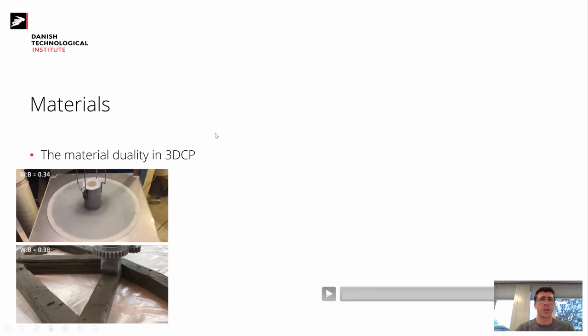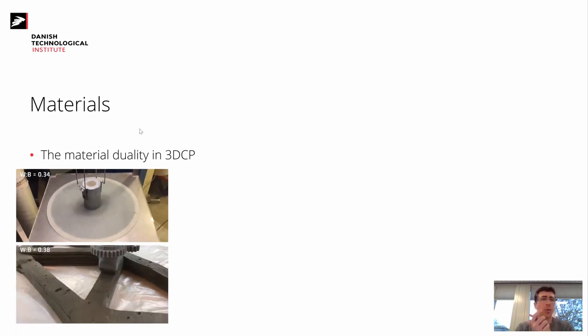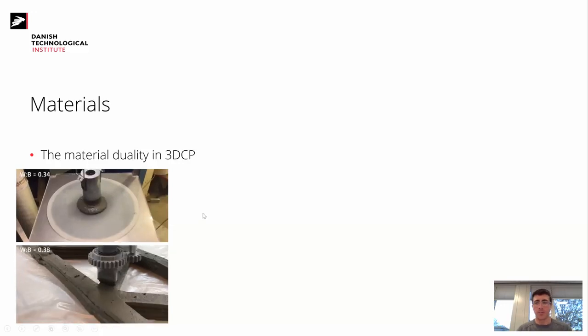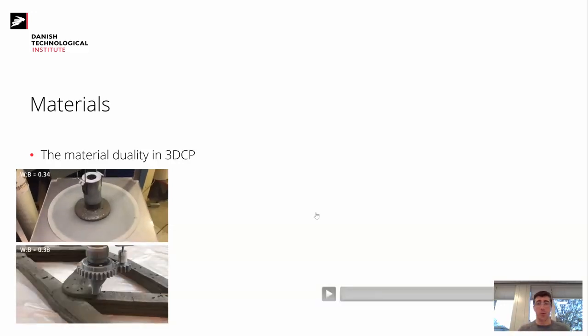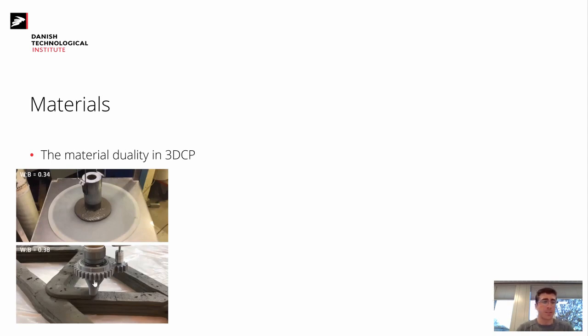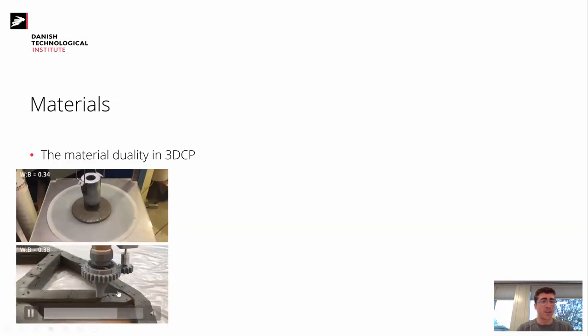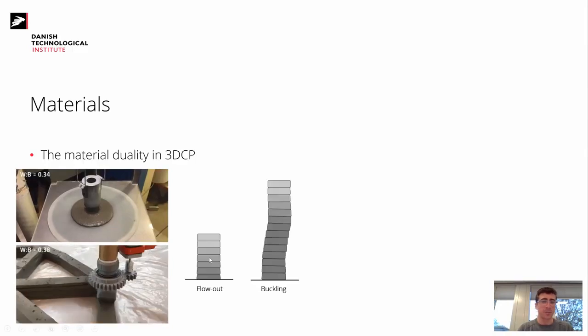So from materials, in a fairly simple way, the challenge with 3D concrete printing, from the very start, is that we have this duality: we want a material that is flowable, so we have no problems pumping it through a stream and then reaching the robot nozzle. But at the same time, we want it to be stiff at the extrusion point, so you can start stacking up layers. And this brings some challenges, because if your material is extremely fluid, you might run into the risk of flow out when you're extruding a material that is too fluid. So you basically make a slump test out of your printing. And if it's not stiff enough, you might still be able to extrude and stack layers, but suffer from an effect called buckling. So you have a slender element that will just buckle out and fail.